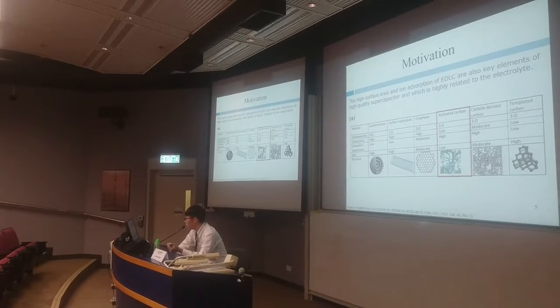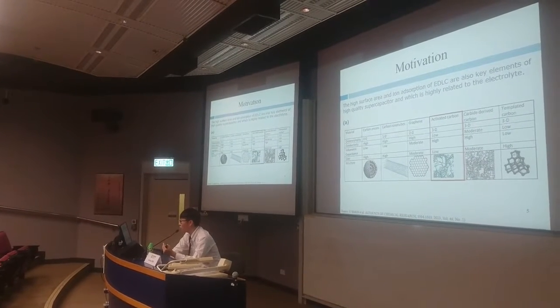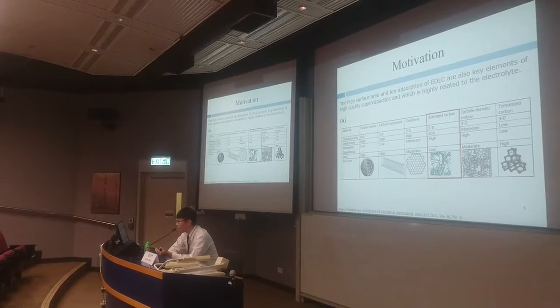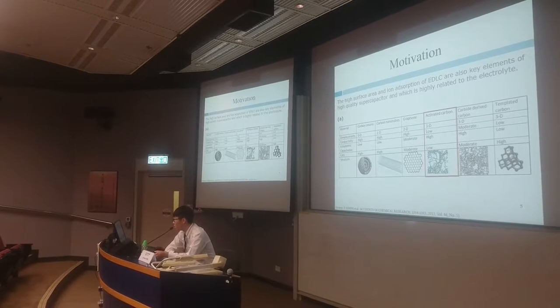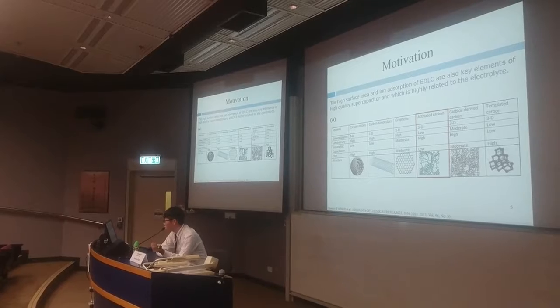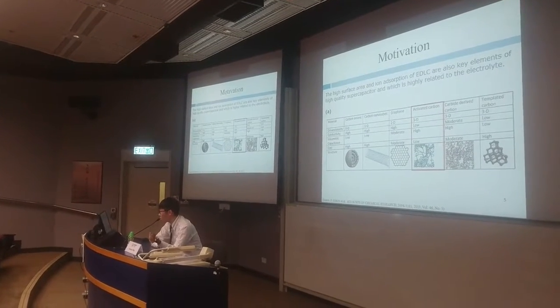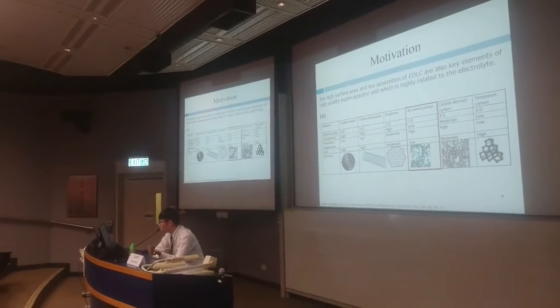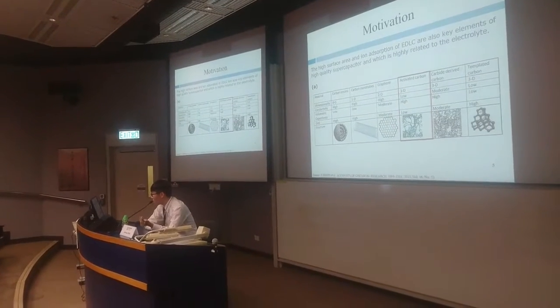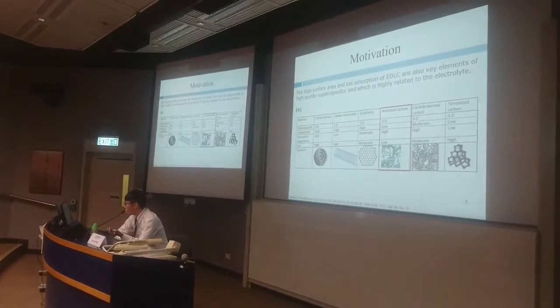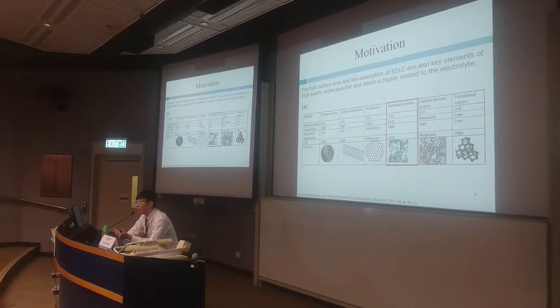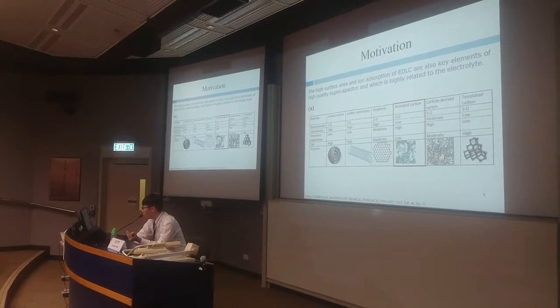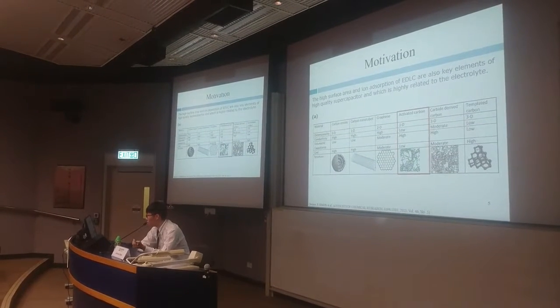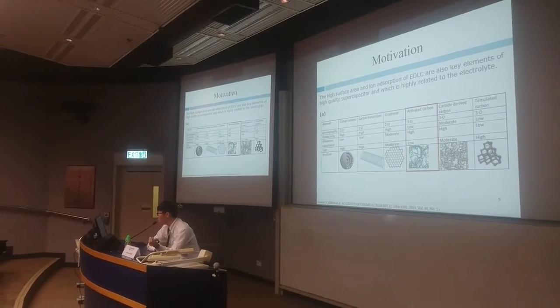In the experimental method, it is difficult to directly observe the ion adsorption inside the electrodes. So in this study, we use MD, molecular dynamics simulation, to investigate the ion adsorption behavior and the capacitance of electrolytes in the different densities of AC electrode.